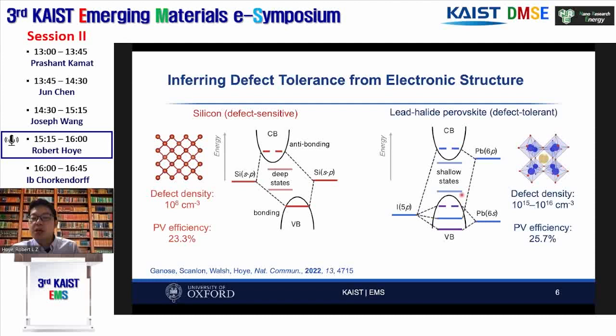And if you look at this shallow state here, it's very close in energy to your conduction band, so you can very easily capture an electron, but it's very far away in energy from your valence band. So the probability of also capturing a hole is a lot lower. And therefore, you can have a high density of these shallow states but still have a low non-radiative recombination rate. Hence, you get defect tolerance.